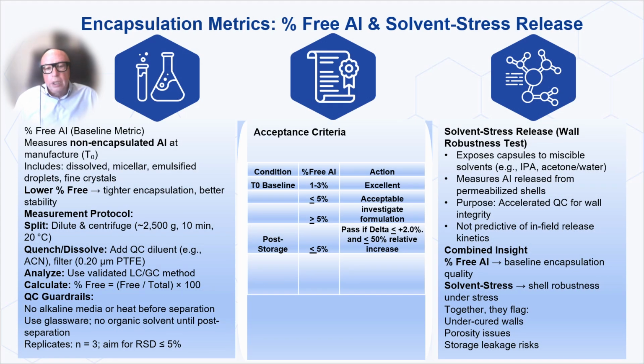Encapsulation metrics, percent-free AI, and solvent stress release. We use two principal metrics to assess encapsulation quality and capsule integrity. Percent-free AI, baseline metric. The principle here is to separately detect AI that's outside the capsules and divide by the total AI content in the formulation. We centrifuge to separate encapsulated from non-encapsulated material, then measure the free portion.